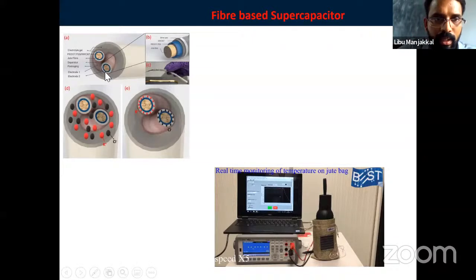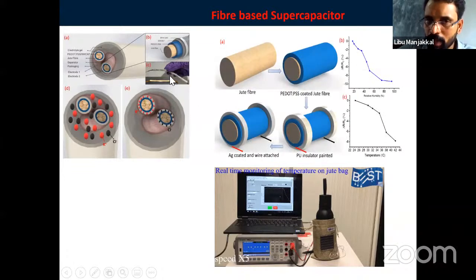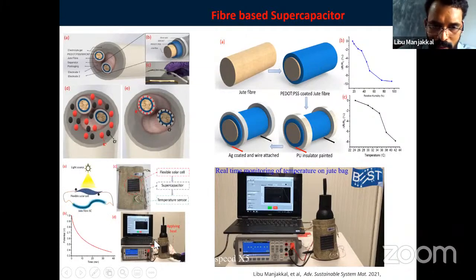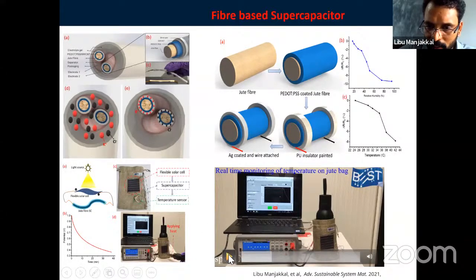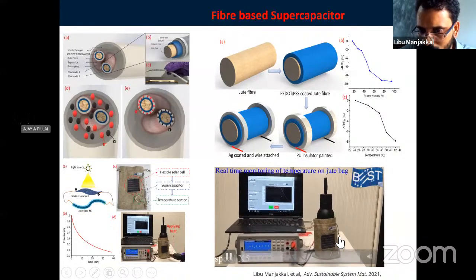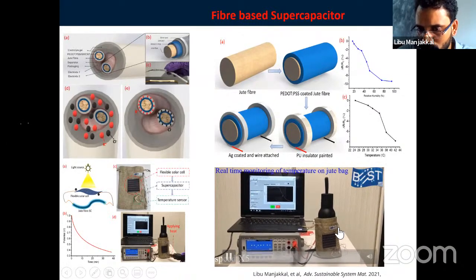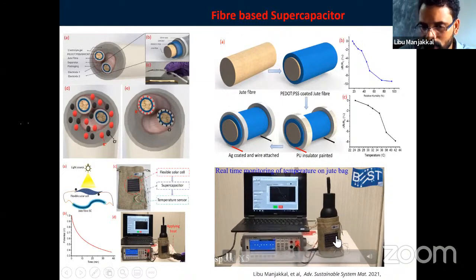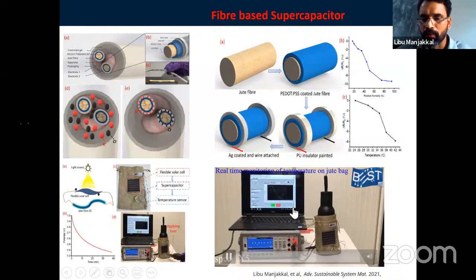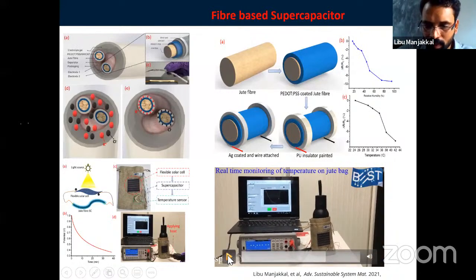So you can see here that I converted a single jute fiber into a conductive fiber by using PEDOT:PSS and carbon nanotubes. And then by multi-stacking this, I developed a cable type supercapacitor. The same fiber acts as a sensor as well, a temperature sensor or a humidity sensor. I then attached this fiber-based device on the jute bag. And you can see here that when I started applying heat on this temperature sensor, the sensor was powered by the supercapacitor, which was charged by using a solar cell. This is used for a self-powered bag or package application.